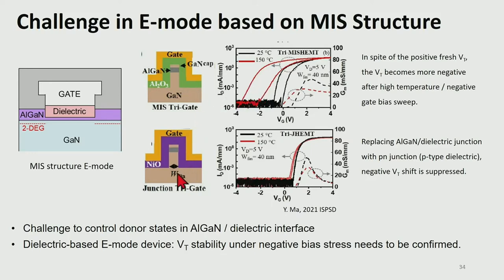But now in the second device, this aluminum oxide was replaced by P-type nickel oxide. Since this is a P-type oxide, now the gate structure is like a P-N junction. And in this device, the negative VT shift is significantly suppressed. This data may explain why we are seeing more stable enhancement mode operation with a P-GaN-based gate structure compared to other enhancement mode approaches with a gate dielectric.